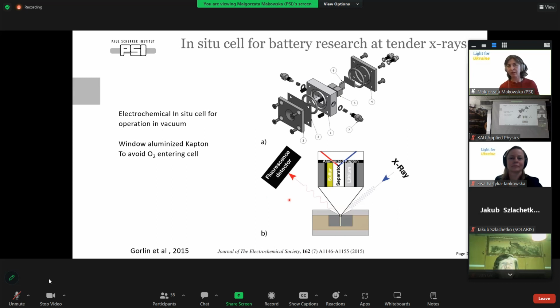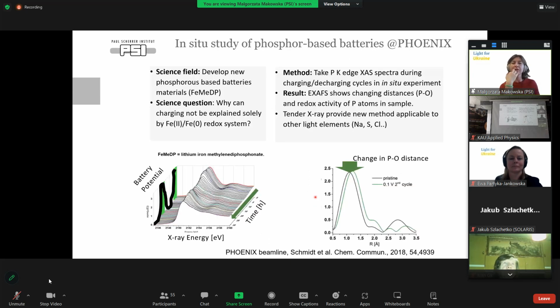So they prepared a little cell for in operando or in situ studies of batteries. And what was interesting, they were studying a battery for which it was believed that the cycling during charge and discharge is mostly based on a redox reaction between iron 2 and 0. However, this was not well explained just with this reaction. And at this beamline, they noticed that during charge and discharge, also the XAS spectrum of phosphorus is changing. And this is, of course, out of the reach for microXAS, while for them it was possible.